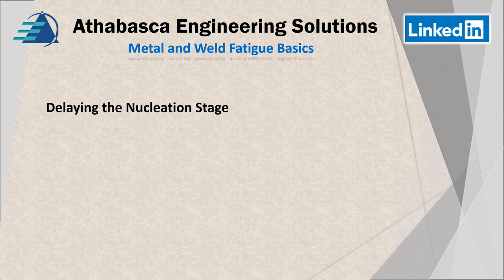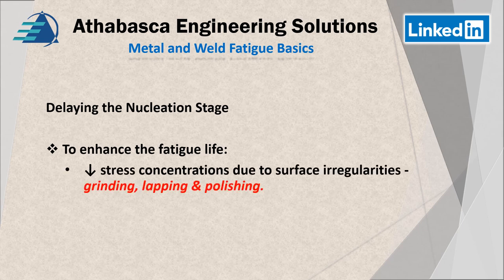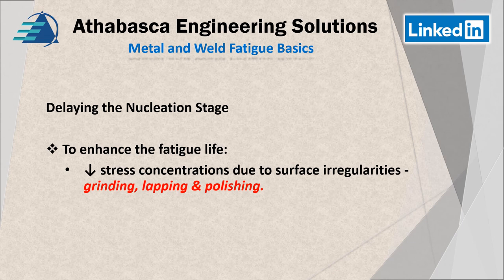There are a few things we can do to delay nucleation and enhance fatigue life. We can reduce the stress concentrations due to surface irregularities, and we can achieve that by grinding, lapping, and polishing the surface of that material. I remember back in university we would polish samples in our fatigue testing equipment, and one of the strategies was to polish that sample as much as we could to reduce the chance of early nucleation — to extend the life of that sample. It was a really neat exercise we had done in the lab.